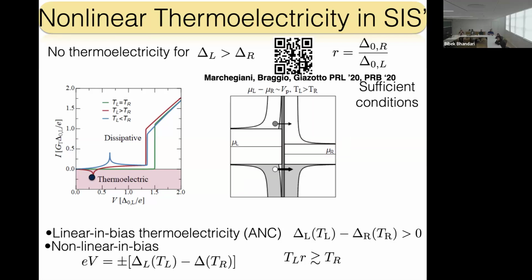This is a configuration of the maximum. So we can also find the maximum thermoelectricity. It is the matching peak, essentially, the value of the matching peak. You see that in the linear case, in equilibrium, there is this peak. But in the case where you configure to get the thermoelectric effect, you have this negative peak, and this negative peak is the thermoelectricity. So this is a sort of nonlinear thermoelectric effect.